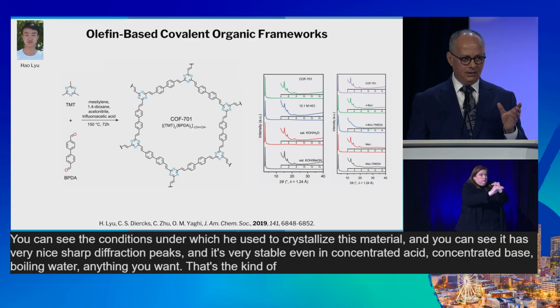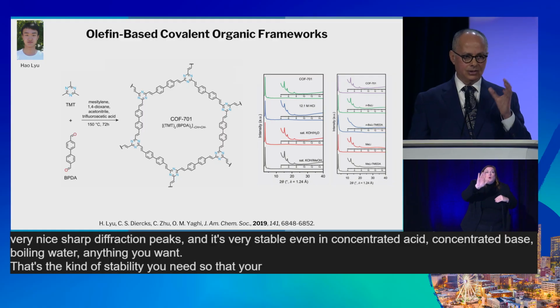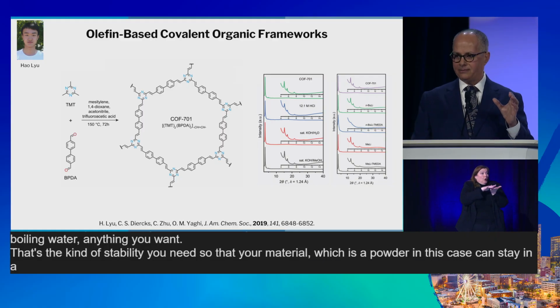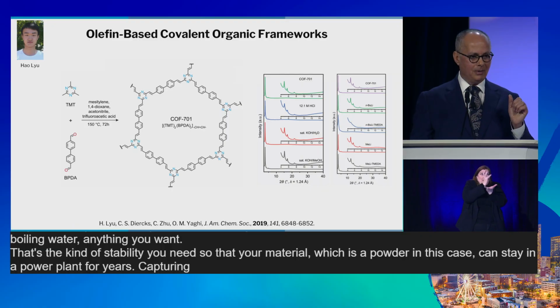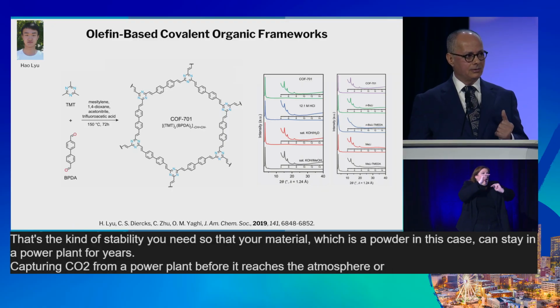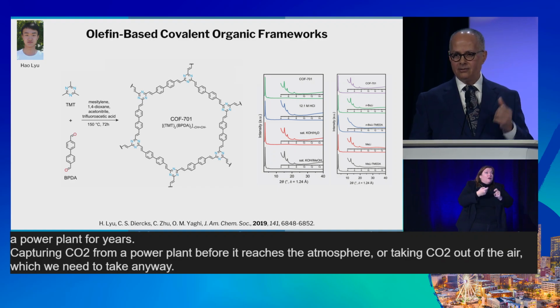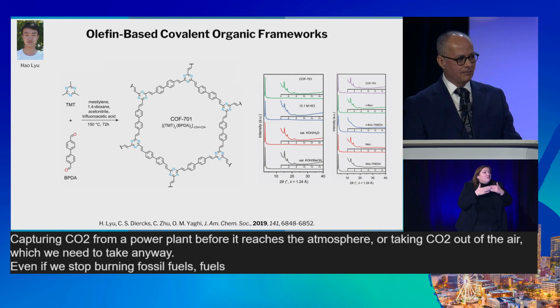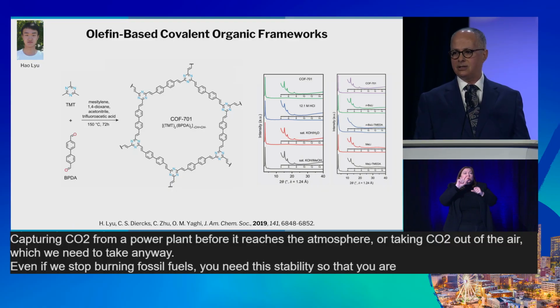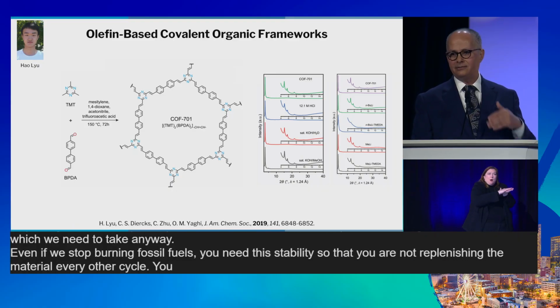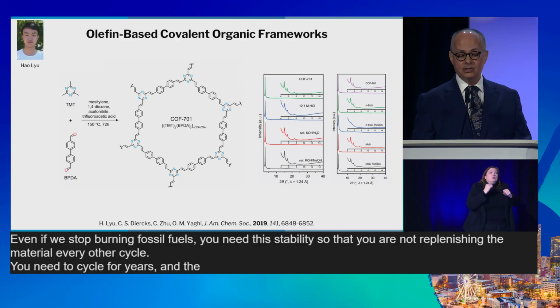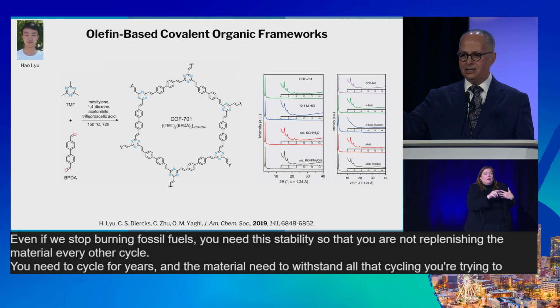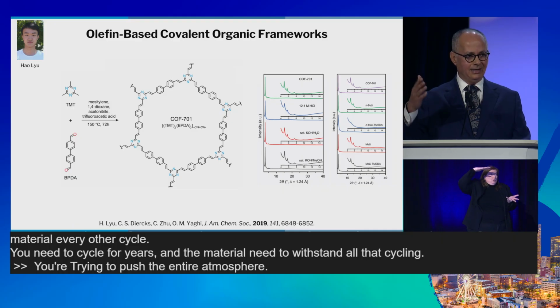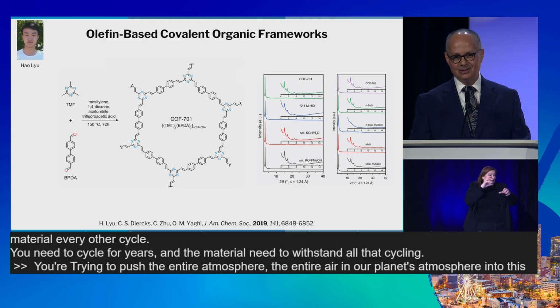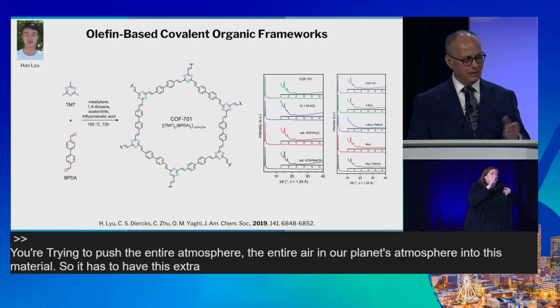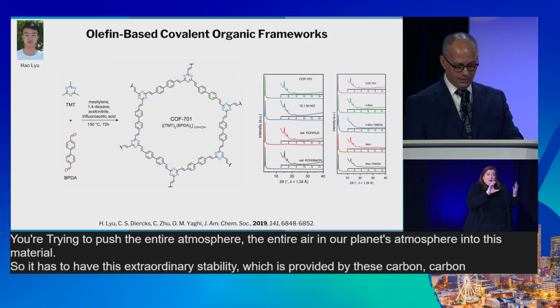That's the kind of stability you need so that your material, which is a powder in this case, can stay in a power plant for years, capturing CO2 from a power plant before it reaches the atmosphere, or taking CO2 out of the air, which we need to do anyway. Even if we stop burning fossil fuels, you need this stability so that you are not replenishing the material every other cycle. You need to cycle for years, and the material needs to withstand all that cycling. You're trying to push the entire atmosphere into this material. So it has to have this extraordinary stability, which is provided by these carbon-carbon bonds.